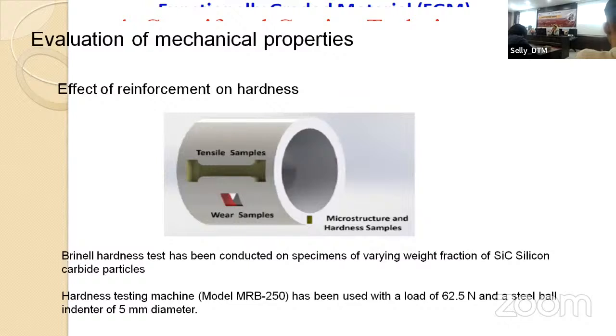What about the mechanical testing? We use the Brinell hardness test. I'm sure you know that. Brinell hardness tests have been conducted on the specimens, varying the weight fractions. In the hardness testing machine, this load and this steel ball indenter of 5 millimeter diameter have been used. In the Brinell test, we use the steel ball and contact the surface area by using the load, and after that we can calculate this area and this depth. So we determine its hardness.